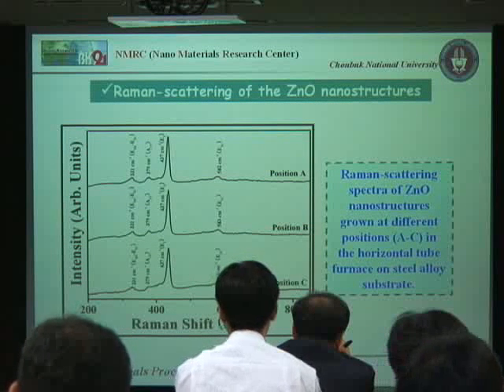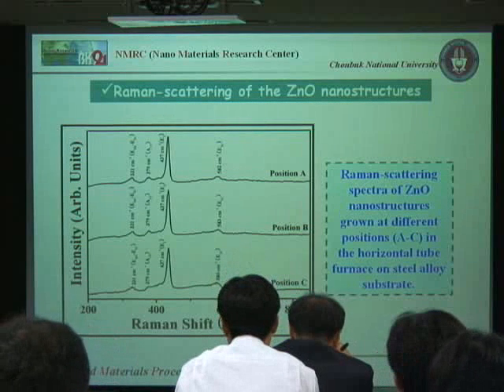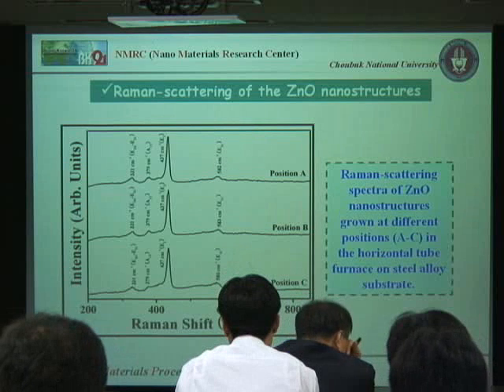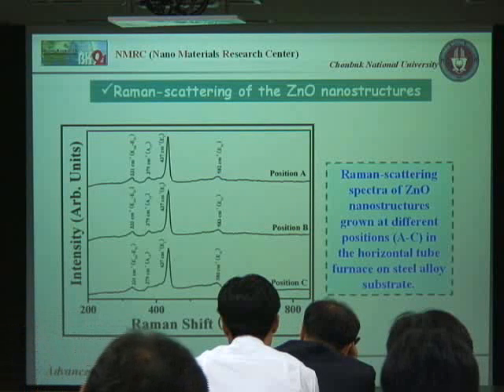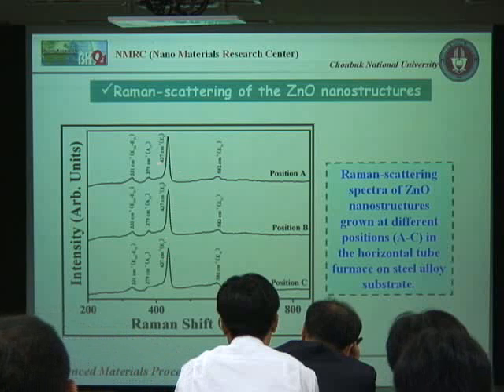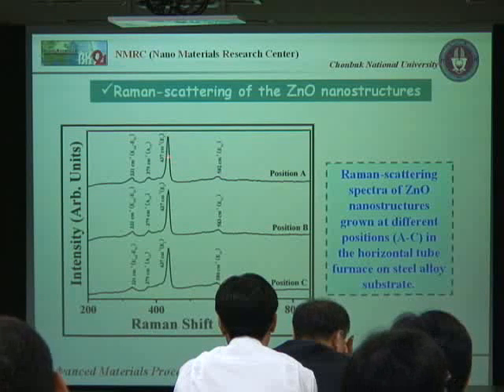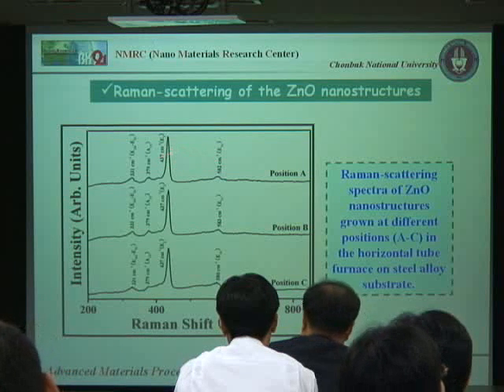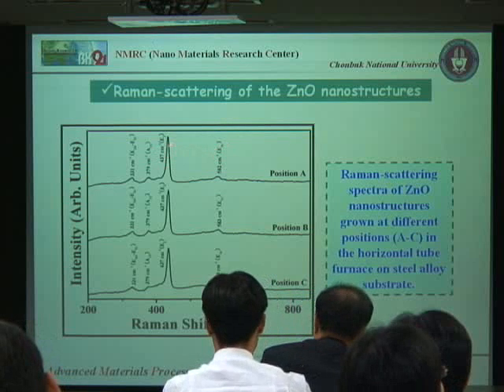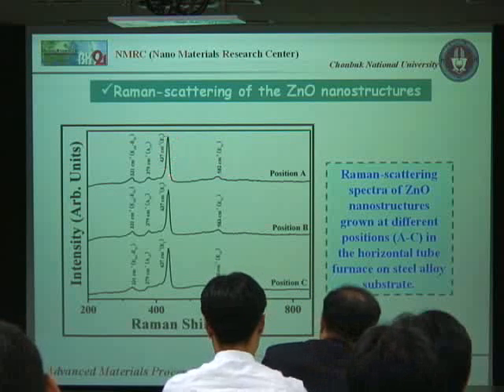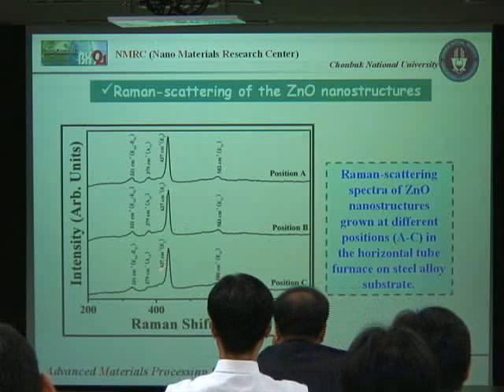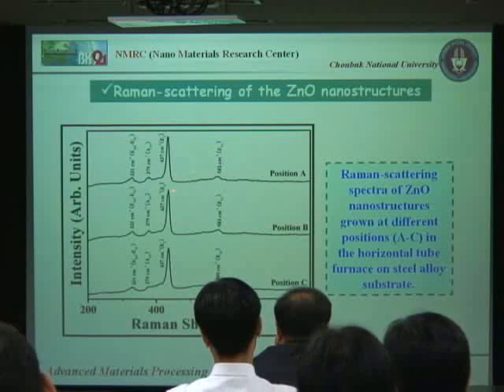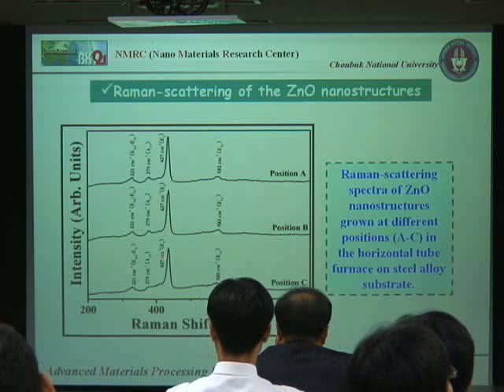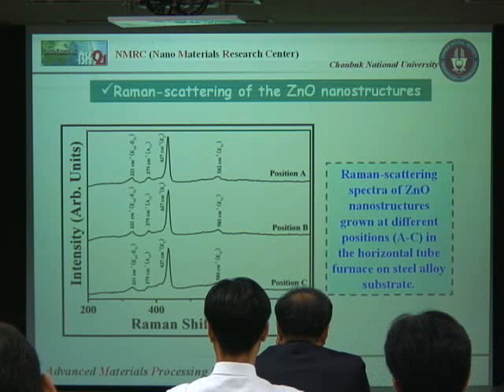To know the optical properties, we did some Raman scattering and room temperature photoluminescence measurement. So in Raman scattering, we got only one peak at 437 centimeter inverse, which is the high optical phonon of E2 mode. This peak is the characteristic peak for wurtzite hexagonal. So in all the cases, we got a dominant and sharp E2 mode, which confirms that our grown nanostructures are wurtzite hexagonal with good crystallinity.